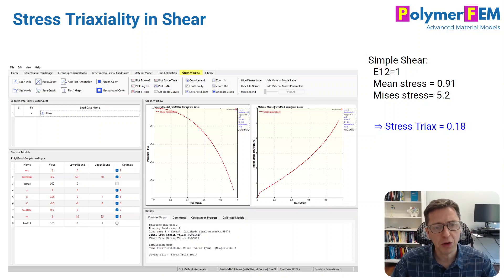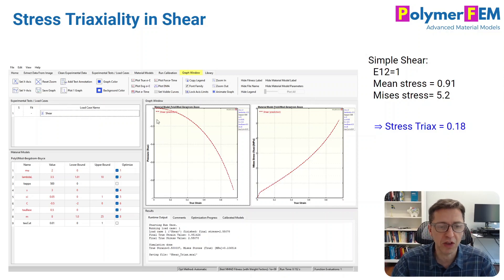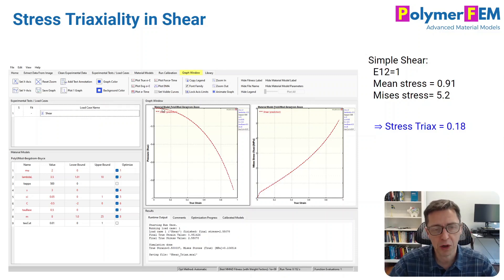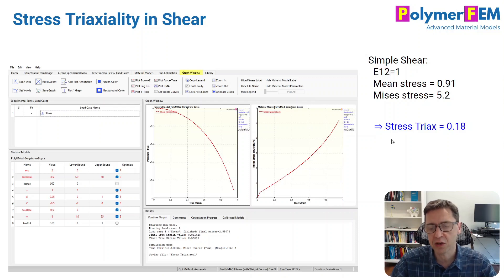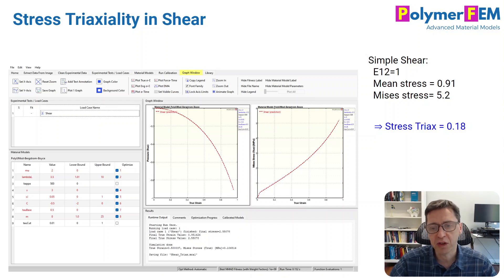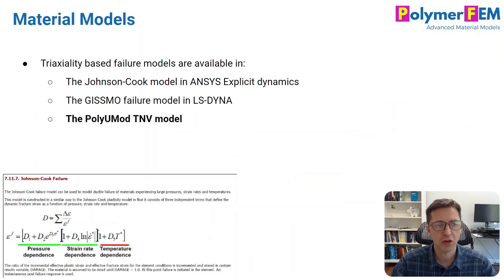The first thing I want to point out — and people get a little tripped up on this — is that the stress triaxiality in shear at small strain is indeed close to zero. But if you do finite shear of a polymer component, you start to develop a uniaxial stress, and that is going to make the stress triaxiality in simple shear depend on the amount of shear strain. It will go from zero up to a value that approaches uniaxial loading at very large shear strains.